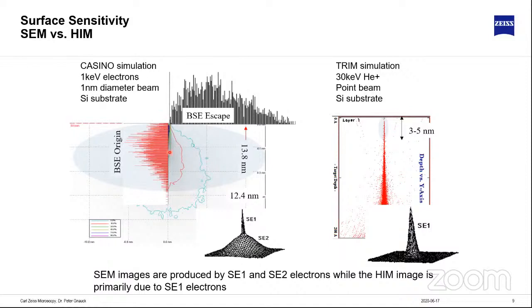Then the beam penetrates deeper into the sample, it's scattered around, and it generates backscattered electrons. Or it generates faster electrons inside the sample. Some of these electrons can reach the surface and they can leave the surface. These are the backscattered electrons, and when they leave the surface, they're also generating a secondary electron. And that means these secondary electrons, the SE2 electrons, they carry all the information about the interaction volume. That means an electron beam always gives an information about surface and volume, so it's always a combined information. And if we want to actually become very surface sensitive, we need to minimize the interaction volume. That means we need to minimize the SE2 contribution. And therefore, we need to go to very low voltages, like 1 kV, 500 volts, 200 volts, whatever, to become surface sensitive with an electron beam.